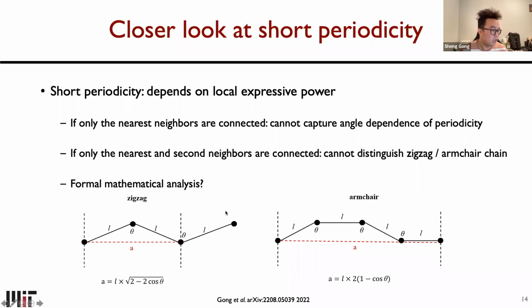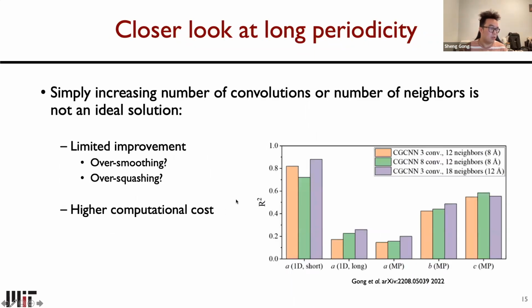Okay, so in addition to short periodicity, we can also have a closer look at long periodicity. As we introduced before, for long periodicity, what we mean is that the periodicity is longer than the receptive field of atoms in the GNNs. And a straightforward way to improve the power to capture long periodicity is simply increasing the number of convolutions or number of neighbors to elongate the receptive field of each atom in the graph neural network. But here we show that simply increasing these two hyperparameters is not an ideal solution.